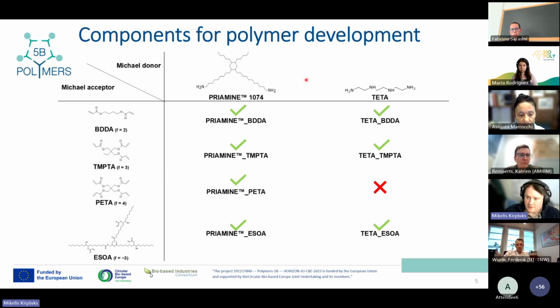we were investigating the aza-Michael addition reaction between amine functionality and acrylate functionality. We want to mimic the polyurethane chemistry, so that we can change the material properties by changing the functionality of the reacting groups. And we want to have a bio-based component and replace the fossil-based feedstocks as much as possible. As one of these feedstocks, we looked into Priamine 1074, which is a commercially produced amine with 100% biocarbon content, and it is being produced from different fatty acids, such as tall oil fatty acids.